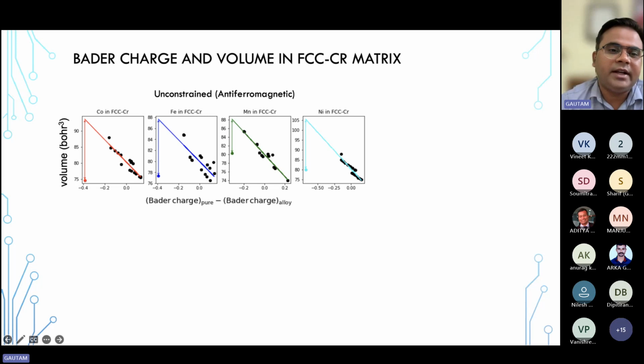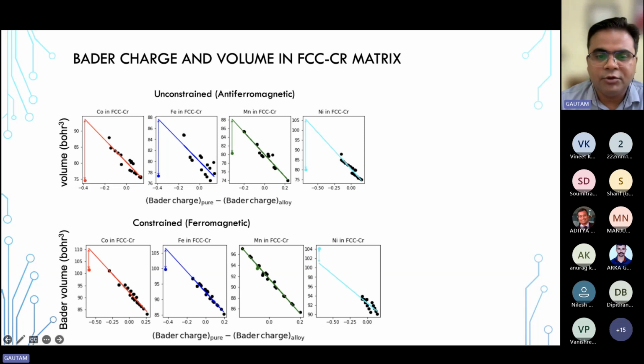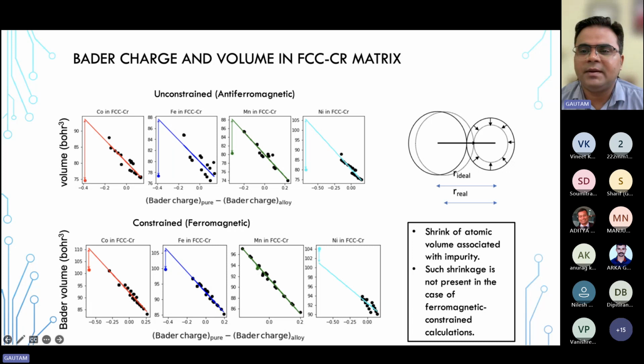We carried out Bader charge and volume analysis on the FCC chromium matrix, and what we found is that the volume of the impurity atom in the center, when surrounded by chromium, shows some kind of volume collapse when the ground state is antiferromagnetic. Because chromium with other elements, the real structure is antiferromagnetic in nature. When we force the ferromagnetic ground state on these elements, we found that this volume change was gradually reduced. The initial hypothesis was that this distortion comes from the impurity atom volume reducing somehow due to some magnetic effect, and that is what leads to the distortion in these kinds of systems.